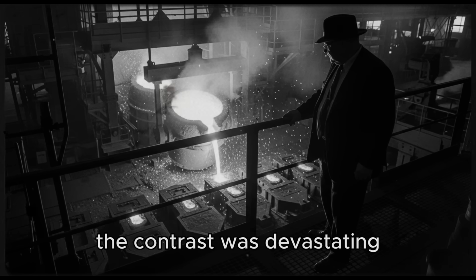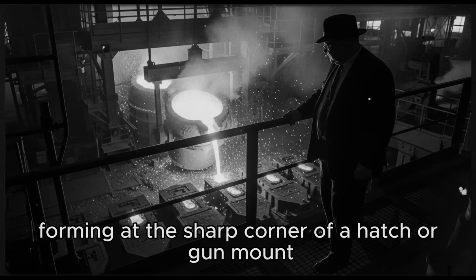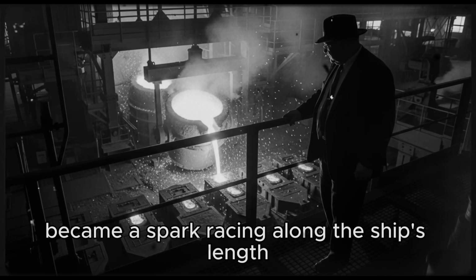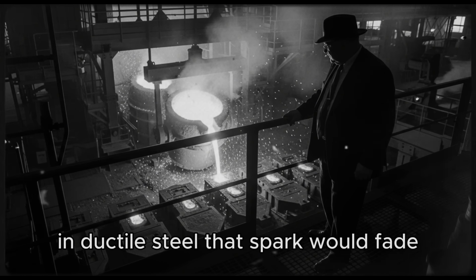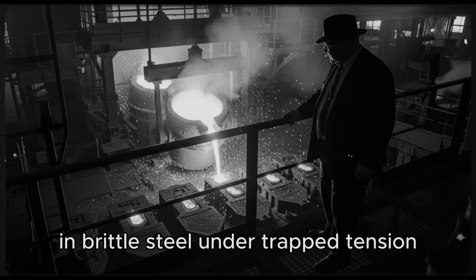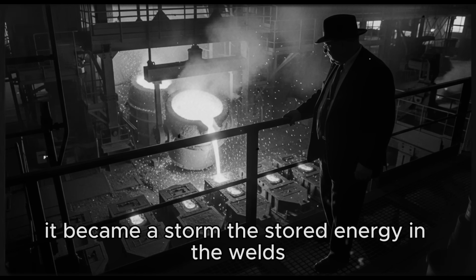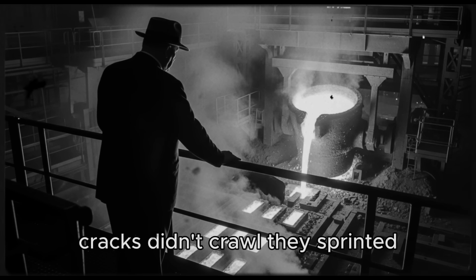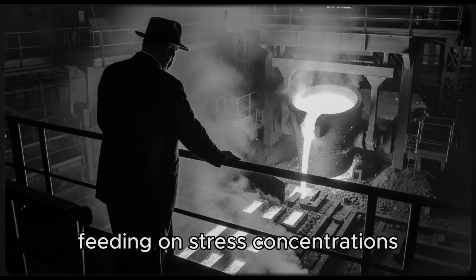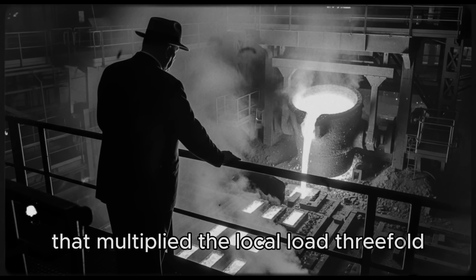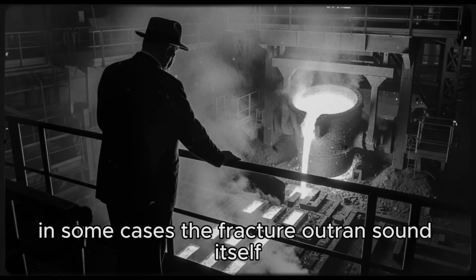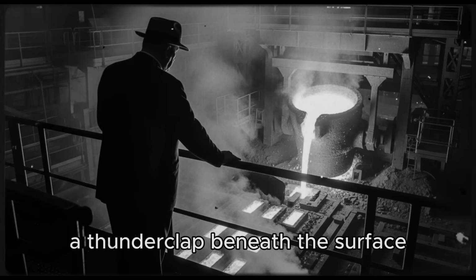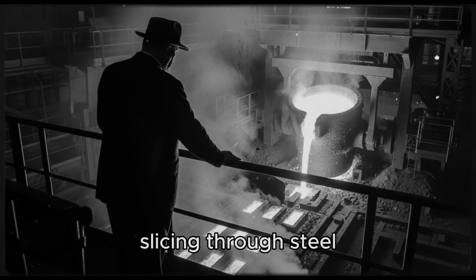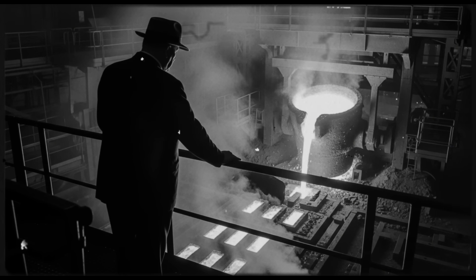The contrast was devastating. A microscopic crack forming at the sharp corner of a hatch or gun mount became a spark racing along the ship's length. In ductile steel, that spark would fade. In brittle steel, under trapped tension, it became a storm. The stored energy in the welds became fuel for destruction. Cracks didn't crawl. They sprinted, feeding on stress concentrations that multiplied the local load threefold. In some cases, the fracture outran sound itself, a thunderclap beneath the surface, slicing through steel before human reflexes could register. The SS Schenectady's fate suddenly felt inevitable.